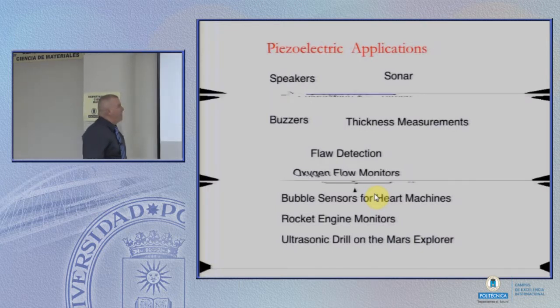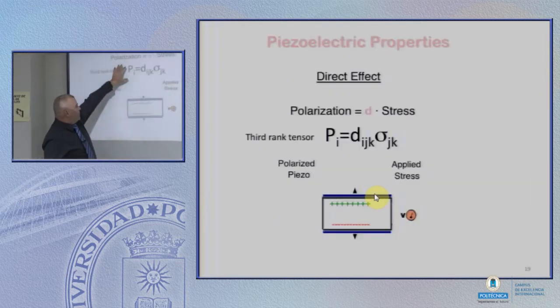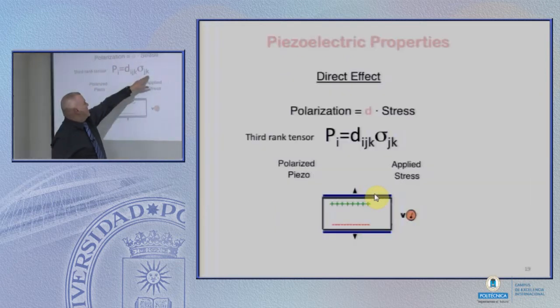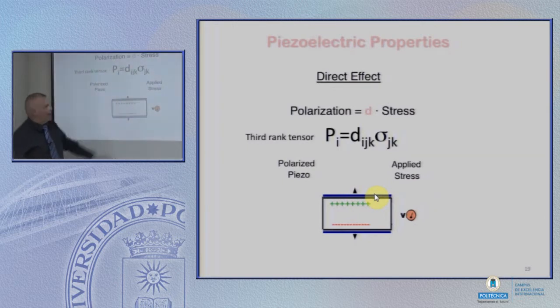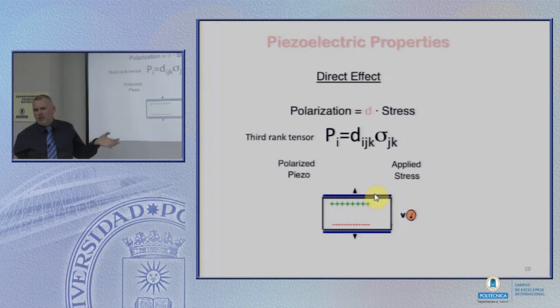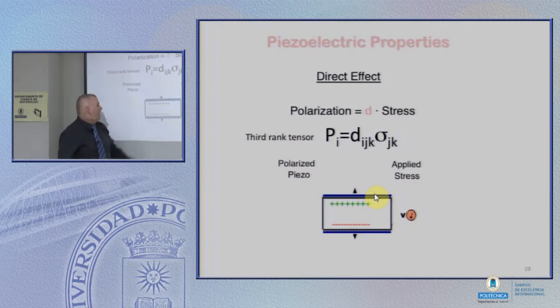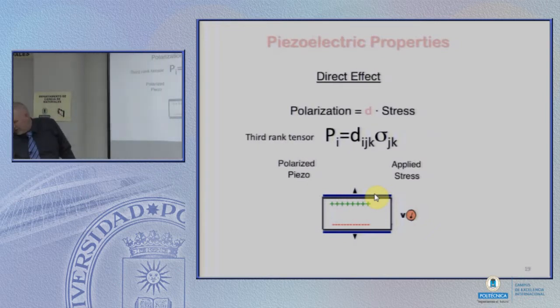There's a direct effect for piezoelectricity, which relates polarization to an applied stress. Usually we use D as the piezoelectric constant. It's a third rank tensor. Usually the form you see it in, it's been collapsed into a second rank looking matrix form, but it really is a third rank tensor. And the idea is if you apply a stress, this is the polarized piece of the material, this is electrical contact, you apply a stress to it, you can measure a change in the field across the material. That's how we use it as a sensor.